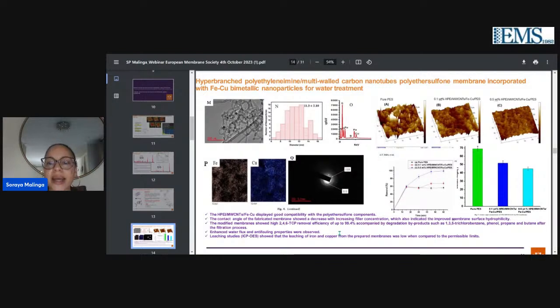So we did a wide array of analysis, which was AFM, TEM as well, proved that the iron and copper coexisted with the multi-walled carbon nanotube. Then we exposed it as well to 2,4,6-TCP for removal. We found that for these membranes, we had enhanced water flux and improved antifouling properties when we exposed them to BSA protein.